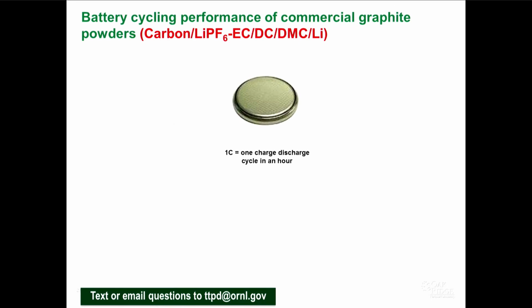So let's look at the battery performance of commercial graphite powder. This is the commercially available sample, from which we made a coin cell. For the battery architecture, we have carbon and lithium. This is a half cell configuration with the electrolyte, and we made coin cells. I'm going to talk about 1C. 1C means one charge discharge cycle in an hour, like how long it will take to charge and discharge in an hour.